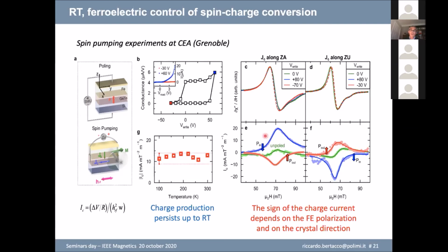with a positive charge production, and for the polarization pointing upwards, the red curve, you have a negative charge production, which means that you can now tune the sign of the spin to charge conversion by playing with the ferroelectric state. So the interesting story is that we are changing something just by changing a variable of state, which is stored in ferroelectric state memory. And along a different crystallographic direction, you have a similar curve, but interestingly enough, it changes sign. That's an interesting demonstration that this is really connected to the crystallographic structure of our material.